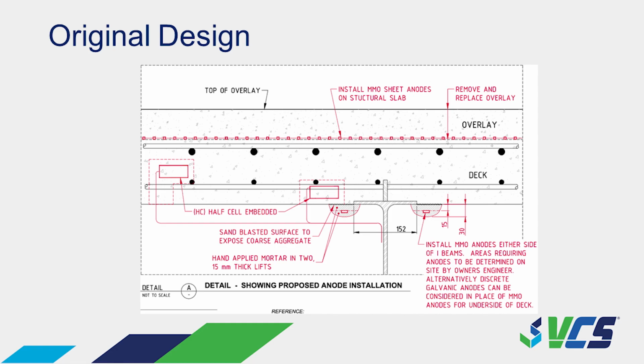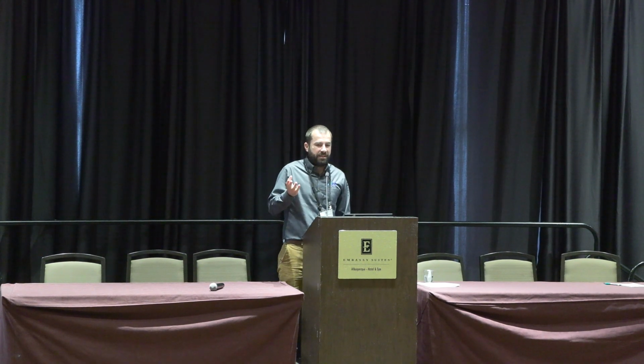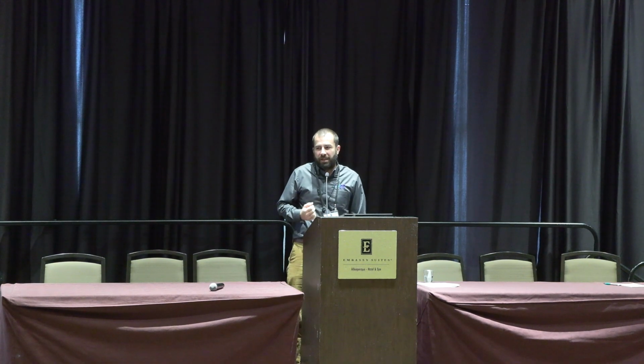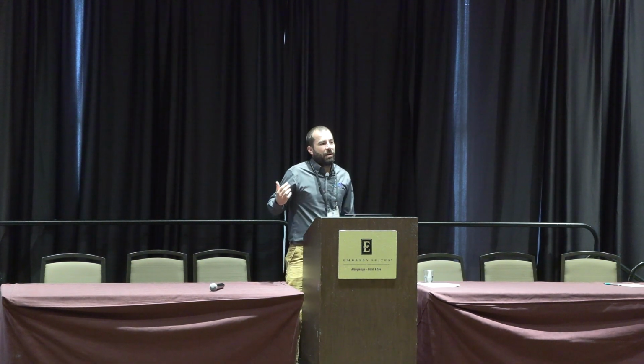But because of the beam corrosion at a localized area, what they also wanted to do was a strip and impressed current system on either side of the girders there. They were designing kind of a half build-out. When we got involved, we looked at that, and putting a build-out concrete mortar on top of an existing deck signals an issue with debonding and trouble getting the surface prep done properly.